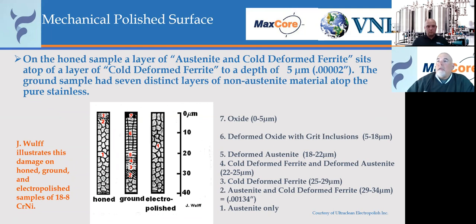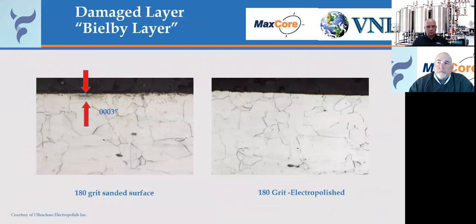If you look at that damaged layer in the magnification, you can see on the 180 grit sanded surface, down to a certain depth, cuts, grooves, and damaged layer on the surface of that particular steel. This is a 180 grit surface that had been electropolished, and you see none of that damaged layer on the surface of that steel.